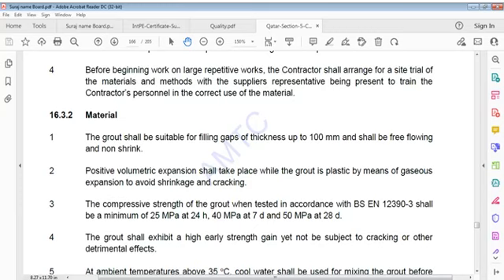Grout shall be suitable for filling gaps of thickness up to 100 mm and shall be free flowing and non-shrink. Positive volumetric expansion shall take effect while grout is plastic by means of gaseous expansion to avoid shrinkage and cracking. Compressive strength of grout tested in accordance with BS EN 12390-3 shall be a minimum of 25 MPa at 24 hours, 40 MPa at 7 days, and 50 MPa at 28 days. Grout shall exhibit a high early strength gain, yet not be subject to cracking or other detrimental effects.